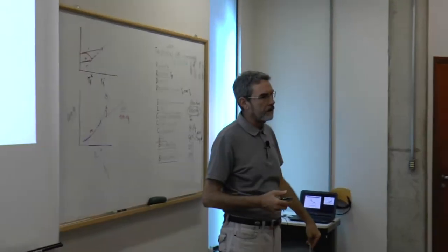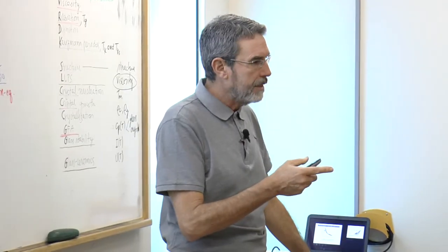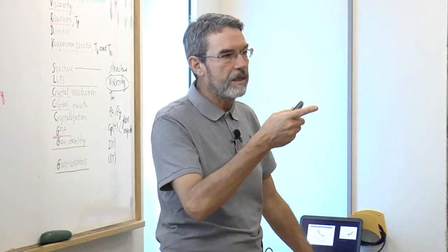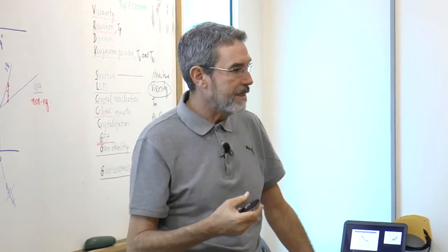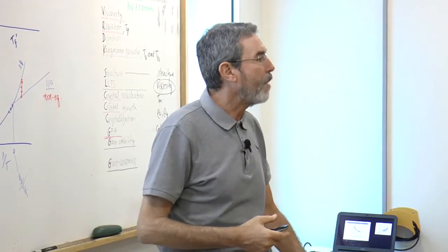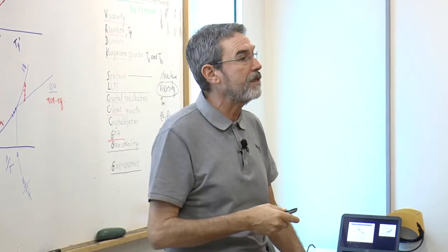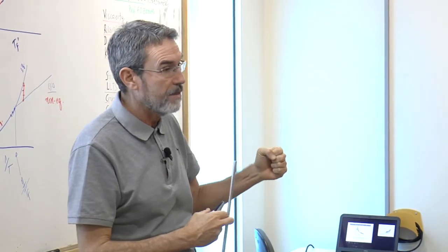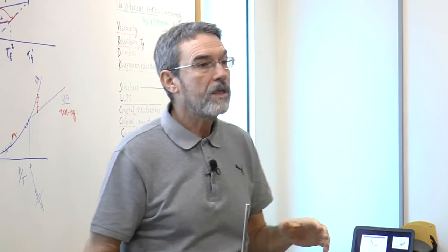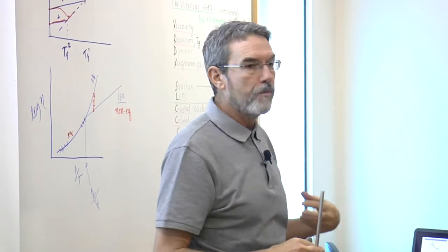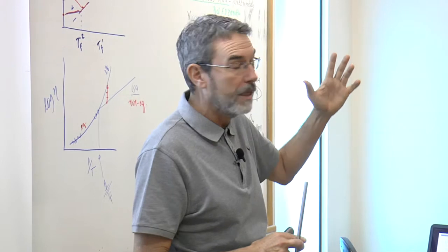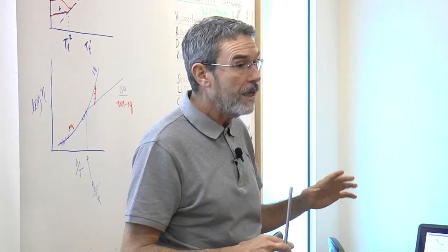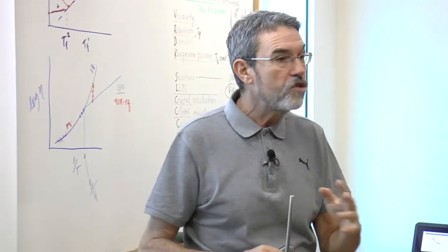There's always some water. And if you're going to do a thesis in the end, like Mina and Maziar, who are developing new glasses, people who are developing new glasses, when you come up with a good glass that you say, this is the one I'm going to characterize for my thesis, you have to measure the amount of water by infrared. You know, you can have nice peaks in the infrared spectrum and see how much water your glass has. Because if you don't measure this, you're not able to reproduce this glass. If you produce a glass in Arizona, a very, very low humidity, and a glass here in Brazil in summer with very high humidity, they'll probably have different amounts of water. Even if exactly the same chemicals are used, these two glasses will be different.